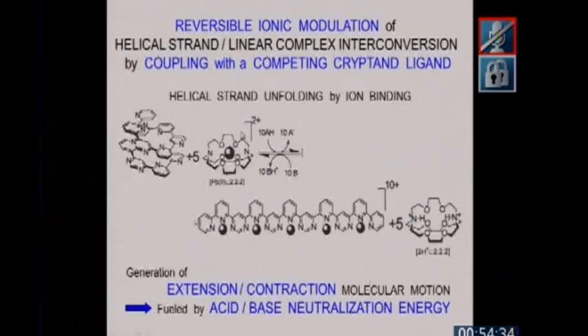If you add a binding agent, this was in fact our first cryptand we made many years ago, 1967, 68, this cryptand will bind lead and remove it, so that this compound is now helical. If you then protonate the bridgeheads here, the lead goes out of the cavity and binds again to the molecule which is outside. If you then add base, you deprotonate these protons and generate the free ligand, and then lead will automatically be picked up again, and so this linear strand will go back to the helical.